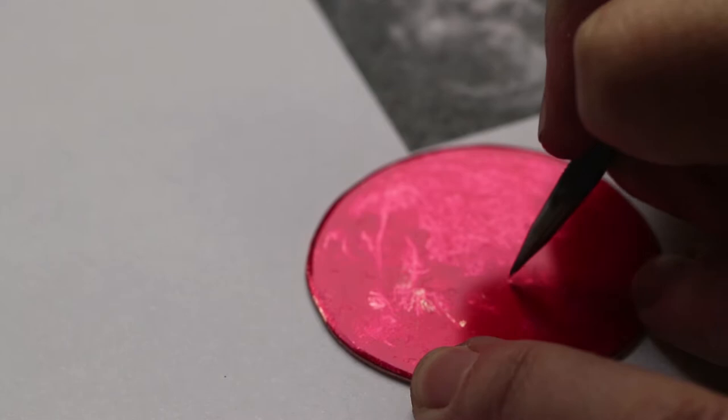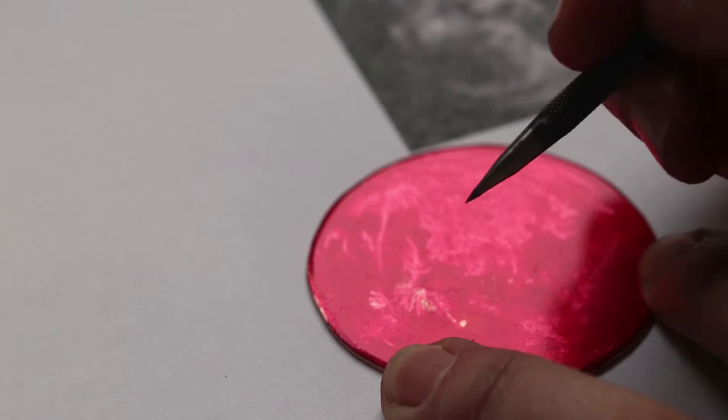I don't have any footage from etching my plate, but I taped up the underside and then put it into a bath of ferric chloride for about 20 minutes before removing the ground easily with a citrus-based cleaner.